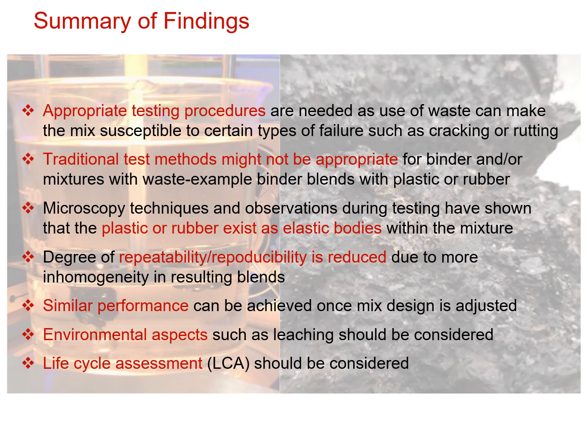I also showed you some examples when the degree of repeatability and reproducibility could be reduced as we're working with waste materials. They are not inherently homogeneous, therefore they introduce more inhomogeneity in our mixtures and blends. We have seen then, I hope that I was able to convince you, that we can see similar performance as the reference mixtures as long as the mix designs are adjusted. For example, in some cases, we had to increase the binder content. So mechanical performance can be achieved.